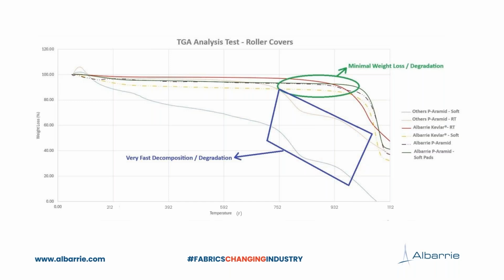So Albarrie's para-aramid soft pads, the one marked on the graph, demonstrated the highest thermal stability, retaining nearly 90% of the weight even at 1076 degrees Fahrenheit. This makes them ideal for high temperature zones where durability and performance are critical.